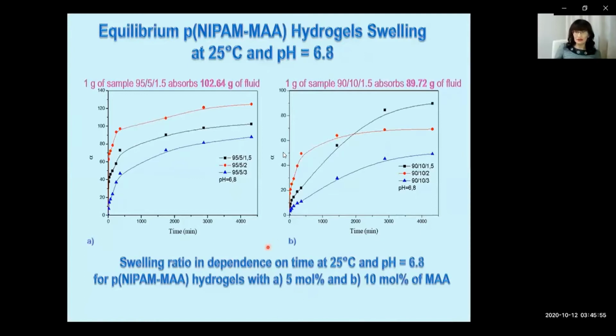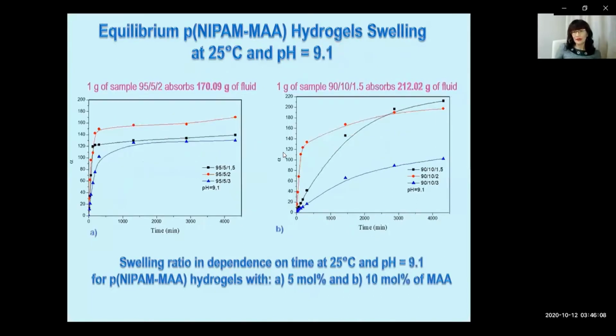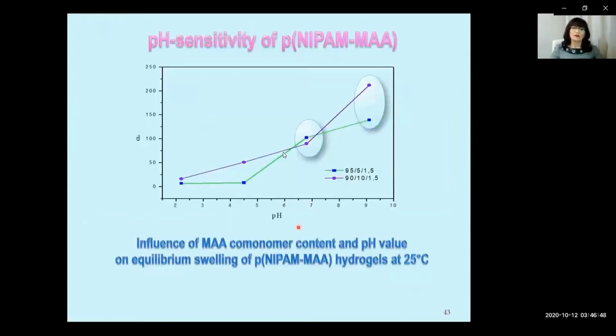As expected, 1 gram of sample can absorb approximately 90 to 103 grams of fluid at maximum at pH 6.8. Hydrogels swell significantly better in the alkaline fluid at pH 9.1. 1 gram of sample can absorb approximately 170 to 212 grams of fluid at maximum. It can be noticed that the equilibrium swelling ratio depends on time, comonomer methacrylic acid content, and pH value. Copolymer hydrogels with methacrylic acid as comonomer are also pH sensitive.